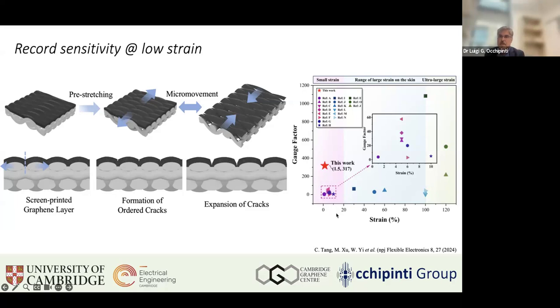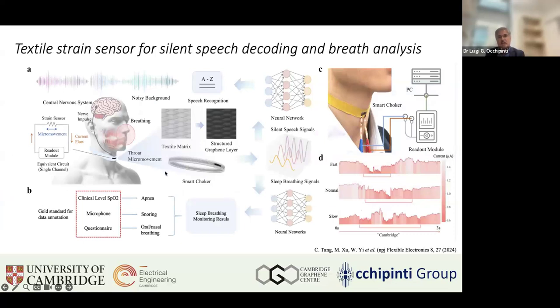Because, of course, as you can see, the amount of strain we are looking at is between 0 and 5–10% up to 20%, and all the existing works at that time were showing a relatively low strain gauge factor in this specific range. While of course in other ranges, there are technologies that can achieve a very high gauge factor exceeding 1000. But in our application, we were looking at the specific range where we could achieve gauge factors in excess of 300, simply because we wanted to apply this work to analysis of speech or analysis of breath.